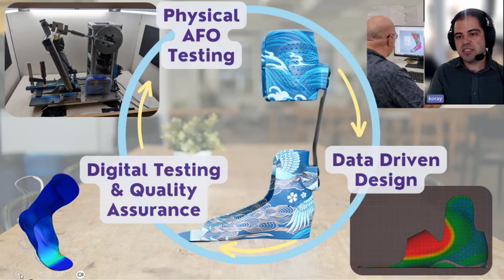So it's not just about the thickness of it. Essentially, that little yellow zone underneath the red, where the dorsum is, if that's not wide enough, then that results in fractures, because the thickness transition needs to occur over longer distances. So the design requests that we get also feed into what we test and how we test it.